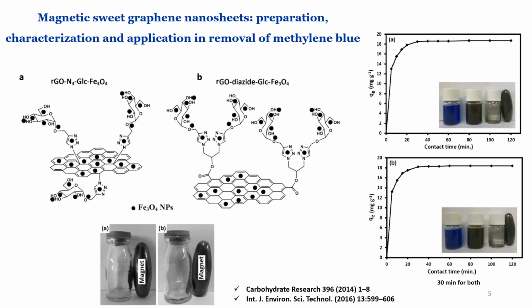And during the click reaction, reduction also happened. Then with the co-precipitation method, magnetic nanoparticles were deposited onto the sheets. As you can see on the right side, after adsorption, we're just placing a magnet close to the vial. The adsorbent readily gets separated from the solution media. And it only took 30 minutes for both composites to reach the equilibrium.